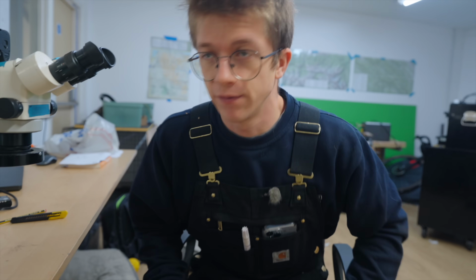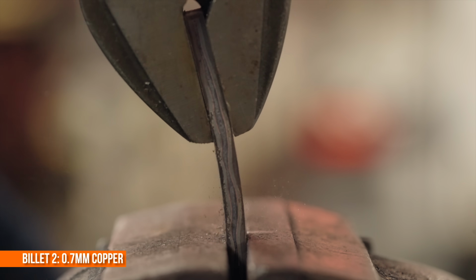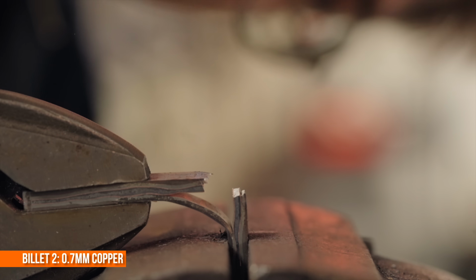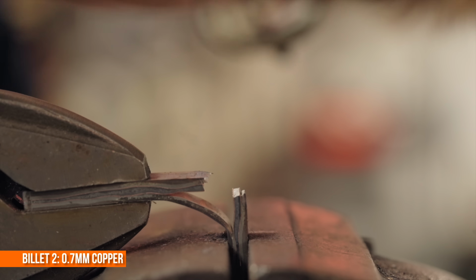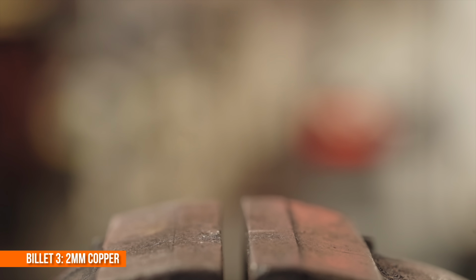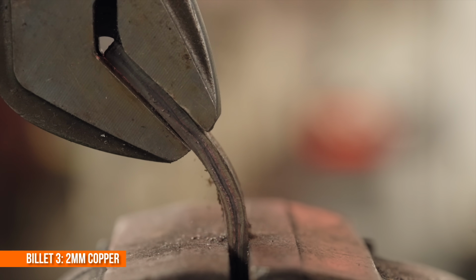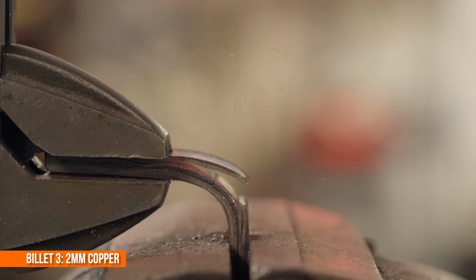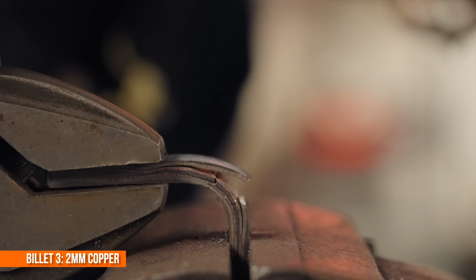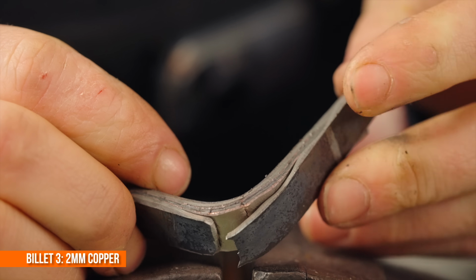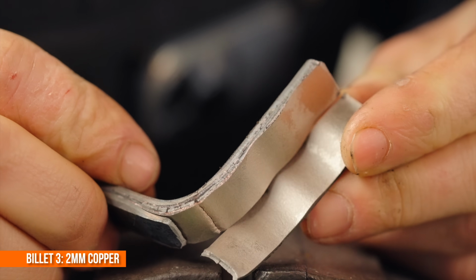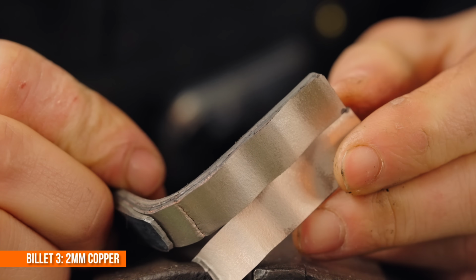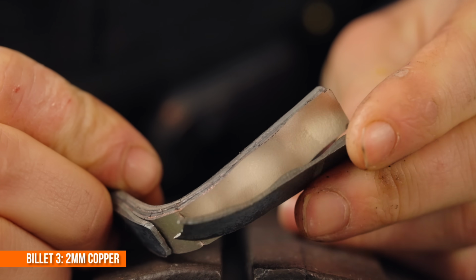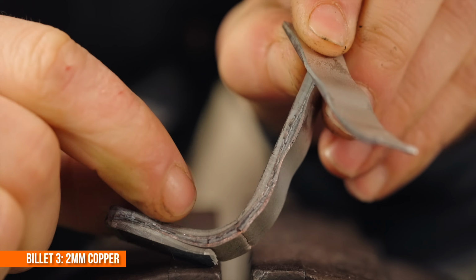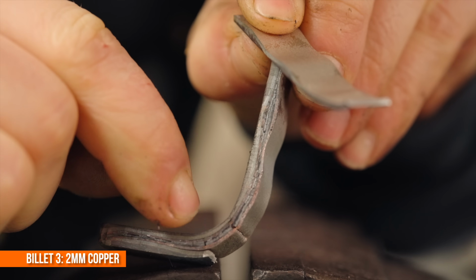See if we can expose any flaws. This is billet 2. Oh, not well, but I mean, we expect a certain amount of it, considering it's now hardened. All right, this is billet 3. It's the one we're rooting for, Jamie. Oh, much better until it wasn't. I mean, I think that held up fairly well. But when it went, it resulted in a complete bond failure between the 2mm copper interlayer and the titanium jacket. We then got fracturing of the carbon steel in several places.